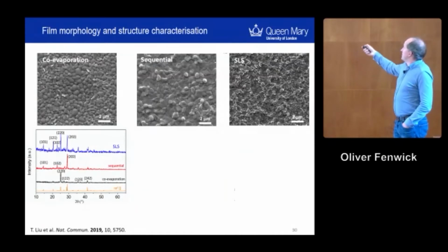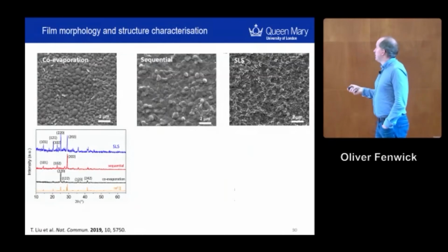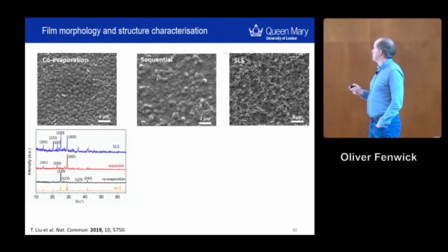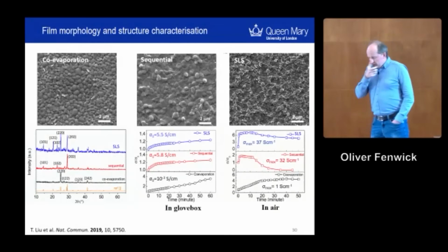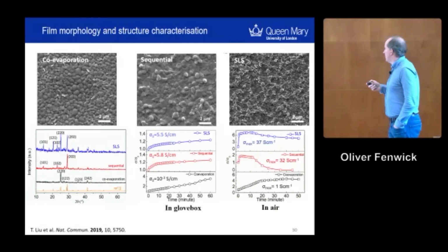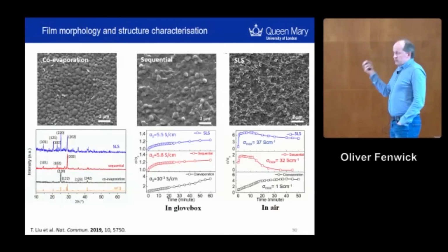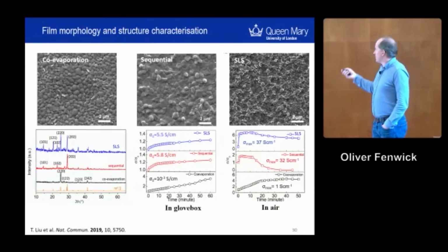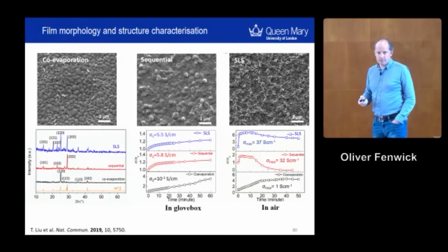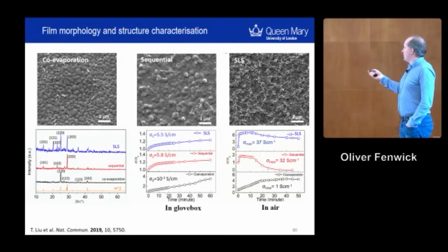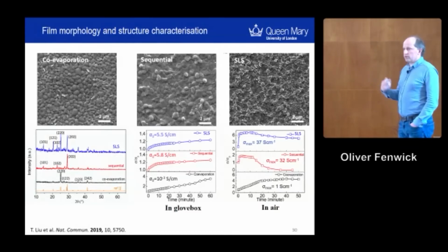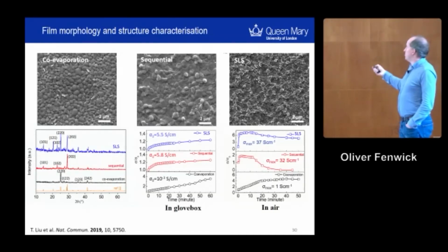So if you look at the SEM images, they have slightly different morphologies on the surface, maybe slightly different grain sizes, but not drastically. On the other hand, they do have quite different preferential orientations on the surface. If you look at the electrical conductivity of these, one thing we notice is it's extremely dependent on the exposure time to air. This is well known already: the electrical conductivity in this system is coming from the oxidation of tin 2+ in the film to tin 4+. And this enables the release of the charge to actually dope the material.